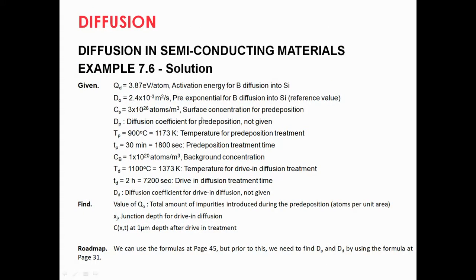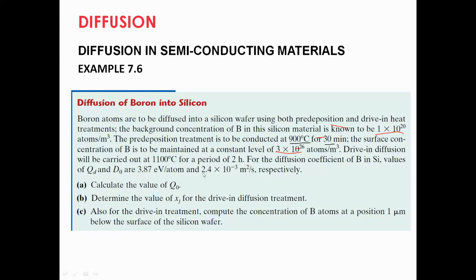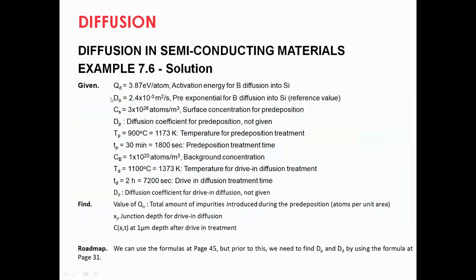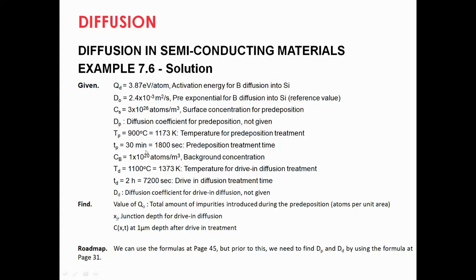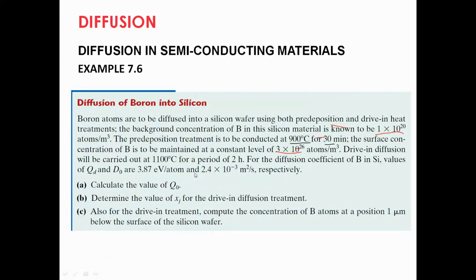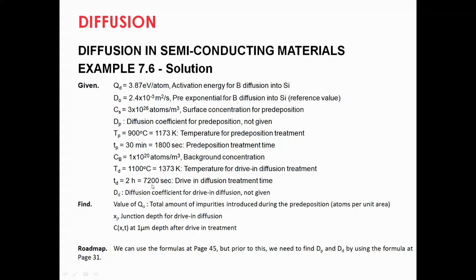Reviewing the given parameters: Qd is 3.87 eV/atom, D₀ is known, Cs is given, tp is 30 minutes, and the pre-deposition temperature is 900°C. The pre-deposition diffusion coefficient Dp is not given. The background concentration is given. For the drive-in treatment, the temperature is 1100°C and the time is 2 hours, which converts to 7200 seconds. The drive-in diffusion coefficient Dd is also not given.